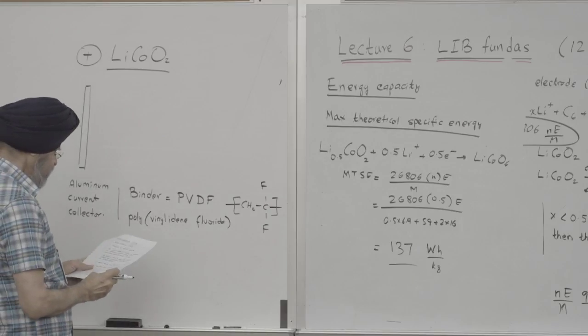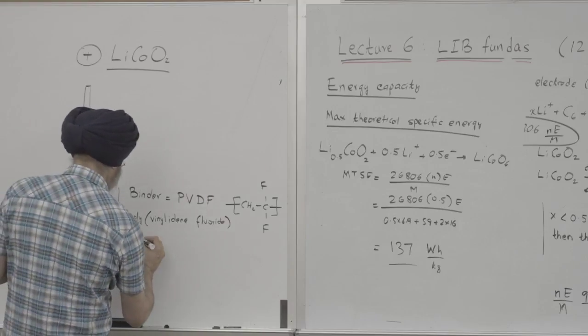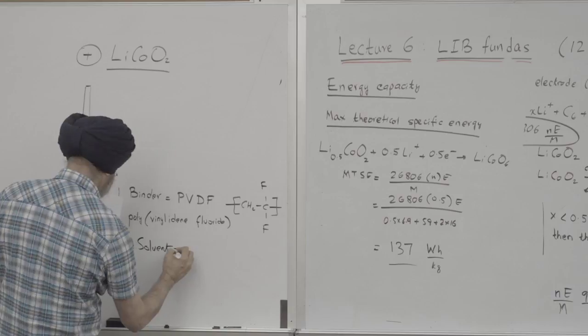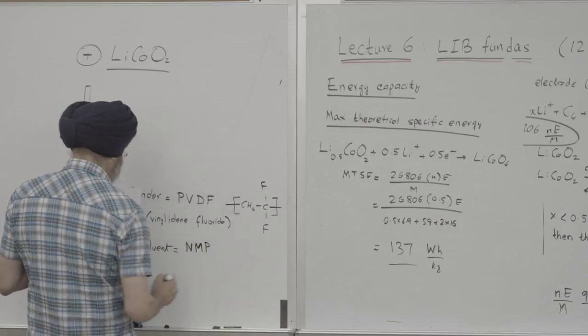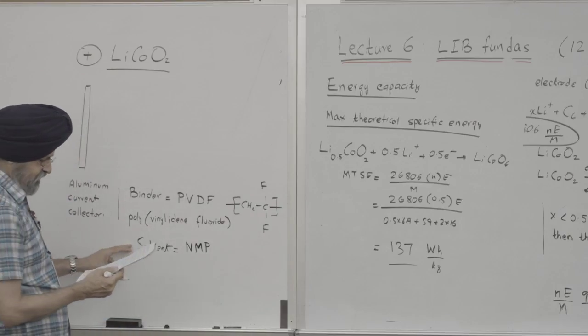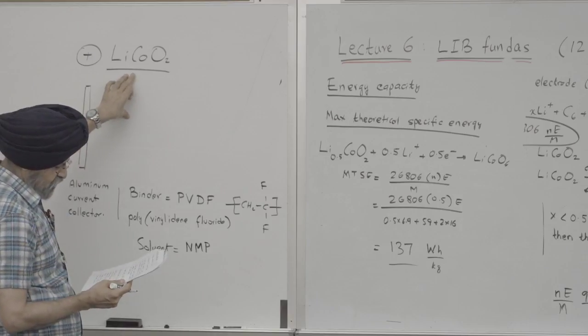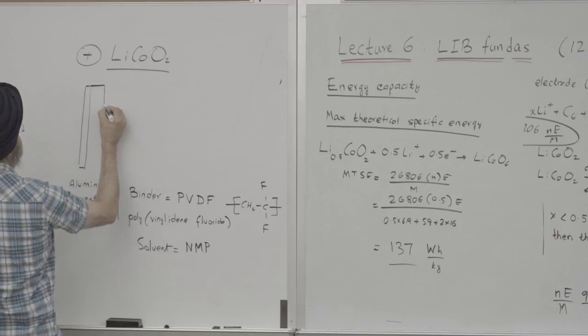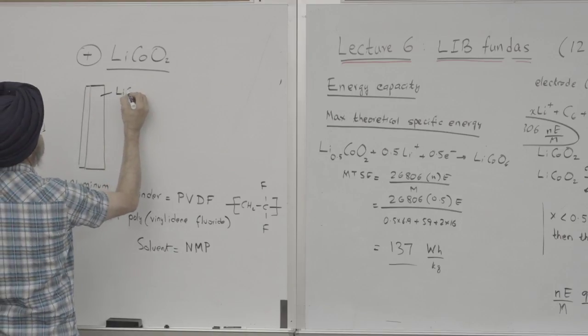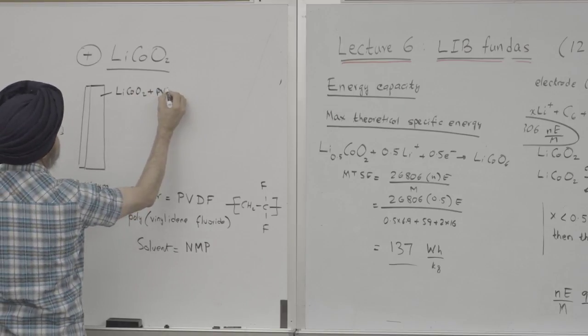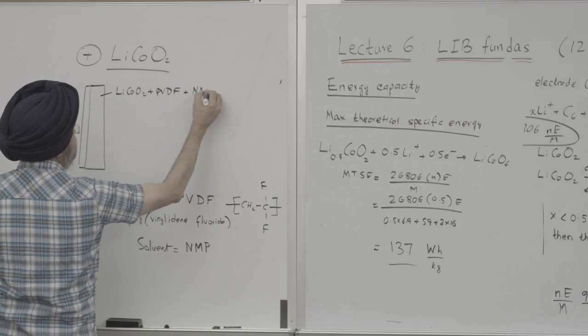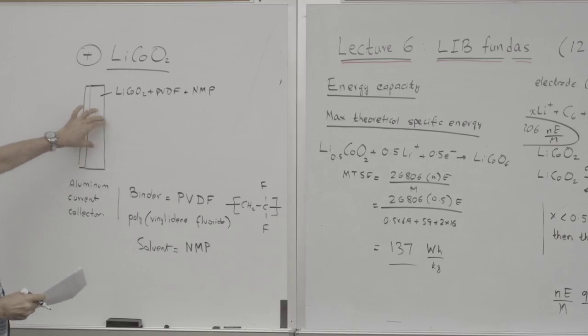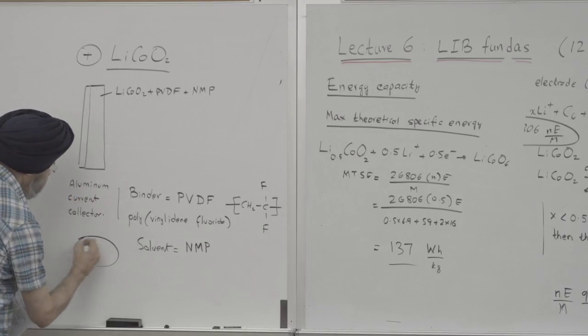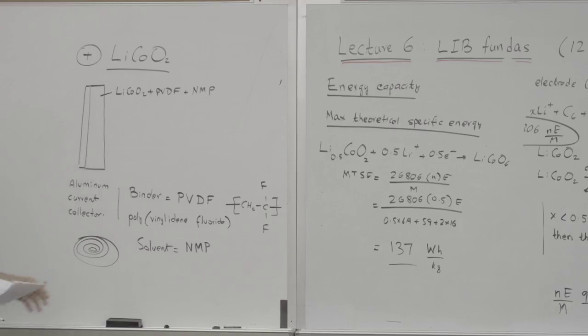And this binder, I think, also needs a solvent. Don't ask me why. So the solvent is NMP. So somehow we have a binder and a solvent, and they all combine together with this lithium cobalt oxide, and it's coated on top of the aluminum. So this is LiCoO2 plus the binder, which is PVDF, plus the solvent NMP. So this concoction, and these dimensions are very, very small. They're like microns, I think. I don't recall the dimensions, but it's extremely thin. It has to be thin because you're rolling this whole thing into a roll. So if it is thick, the stresses would be too high, right?